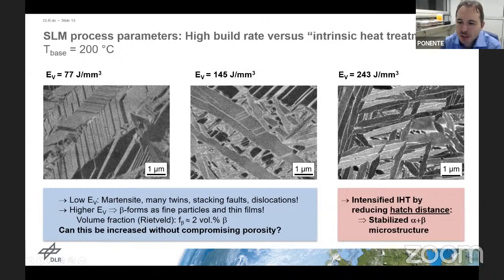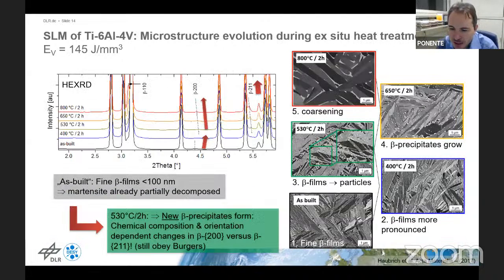So next thing we did is, of course, for the titanium systems, we need a few heat treatments. We need a stress relief heat treatment in the beginning in order to avoid part distortion, for instance. It's generally done at subtransus temperatures of around 500 to 650 degrees Celsius. And we investigated further heat treatments in order to obtain very stabilized alpha-beta microstructures, without sacrificing this very fine grain structure that you generally get in the SLM materials.